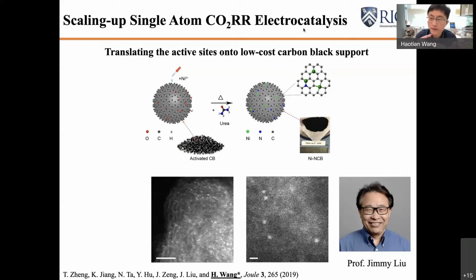So two ways. Number one is the graphene substrate is, even though it's very effective, still very expensive. So how about if we can translate those single atom sites from the graphene nanosheets to very low-cost carbon blacks? So the carbon black substrate is thousands of times cheaper than the graphene and can be easily large-scale produced. Then we can realize large-scale and low-cost production of those single atom catalysts.